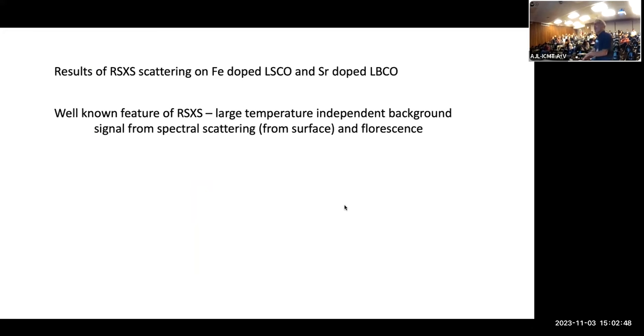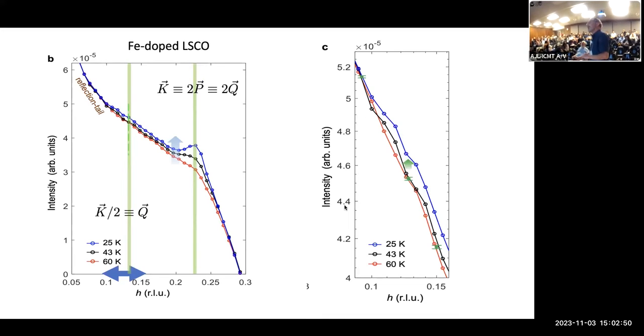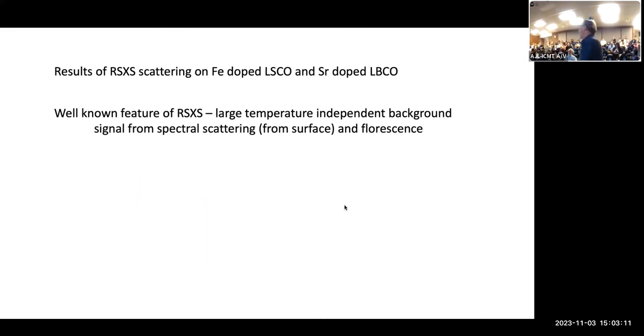Okay, so let me blow up this region. What you can see is the scattering strength at this wave vector is temperature independent as I lower it from 60 Kelvin to 43 Kelvin, and then there's excess scattering when I go down to lower temperature. It's well known that this is a feature of resonant X-ray scattering. You have a big fluorescence background, which is Q dependent, but temperature independent.